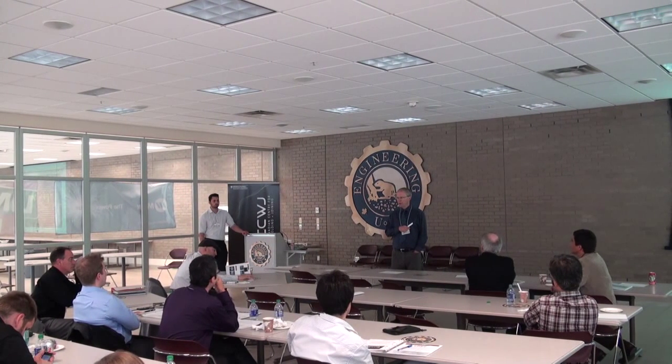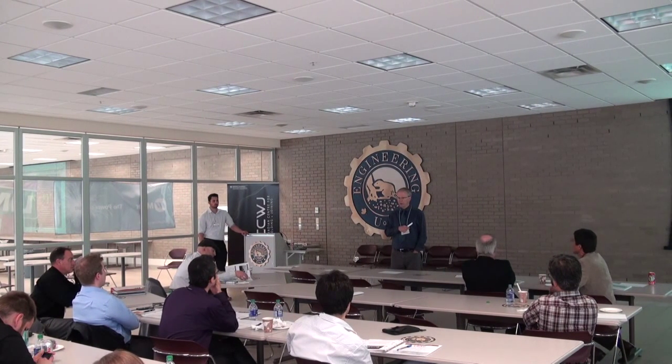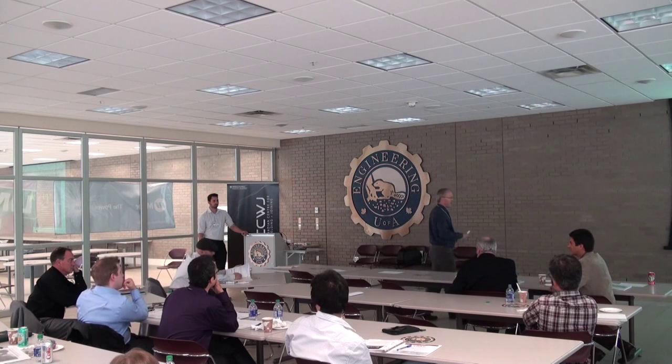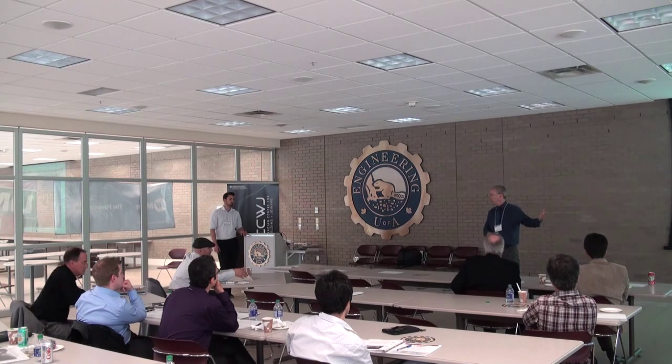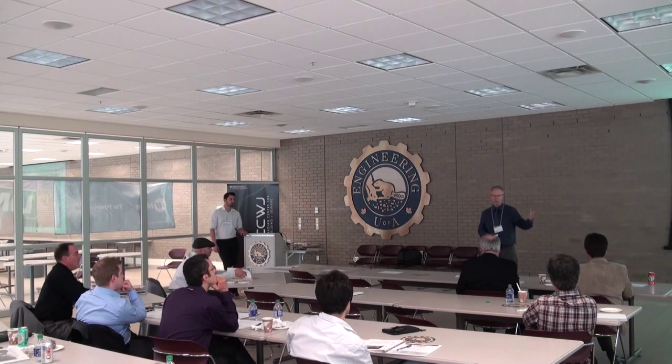Yeah, you can weld just about anything if you really pay attention to what you're dealing with. With no records, you have to take the filings off and send them to the lab to determine what the carbon equivalent is. And that's where these guys probably got caught. They probably just said, well, here's the spec for the pipe, there's no reason to believe it had that high a carbon equivalent, so they didn't factor that into it.